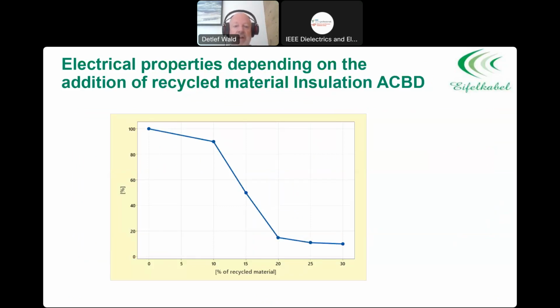Here is a short summary or sneaky peek, and I'm just looking now and I'm perfectly in time, a short sneaky peek about the electrical properties depending on the addition of recycled materials of AC insulation and AC breakdown. So the addition was here, and there will be more, like I said, in that secret paper that will be presented at the beginning of November. So what was done here was of new, not used polypropylene cables. A certain percentage of recycled material has been added to virgin polypropylene material afterwards, and a new cable was produced.